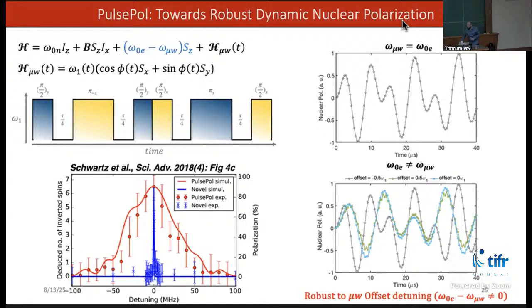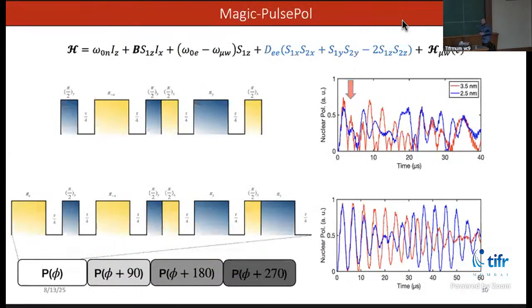So we thought of improvising upon pulse pole such that it can be tolerant to the electron-electron coupling. And here is a comparison. If you have normal pulse pole, the efficiency goes down the moment we have electron-electron coupling. But we came up with a variant of pulse pole which we named magic pulse pole, which includes basically some phase cycling and adding some compensation factor. You can see the efficiency, which is the maximum transfer, remains almost as efficient as the technique based on a single electron. So even if we include the electron-electron coupling, the transfer rate to the neighboring nuclei is very efficient.